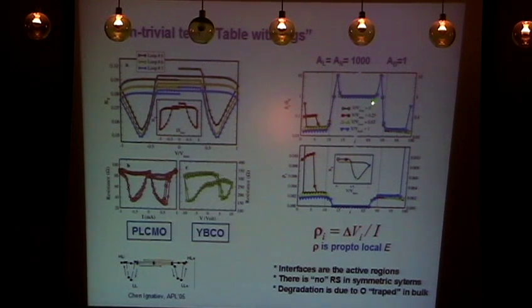because that is where all the action happens. So this is the accumulation that you get in the interior part of the bulk, but here is where all the action happens. Let me now drive you through half of the cycle of hysteresis. We start at 0 voltage at the black dot. The black dot corresponds to this profile of density where you see a pile-up of vacancies on the left. The pile-up on the left comes because before that you had the negative voltage part, which produced this accumulation.